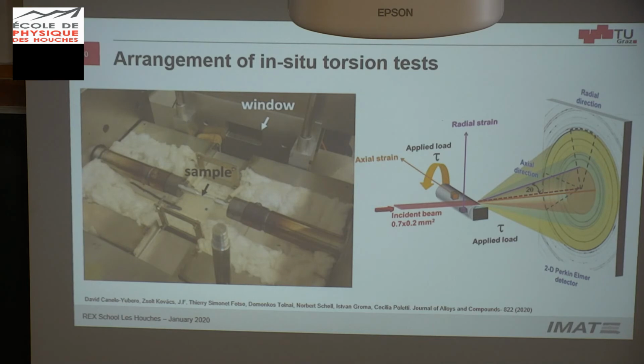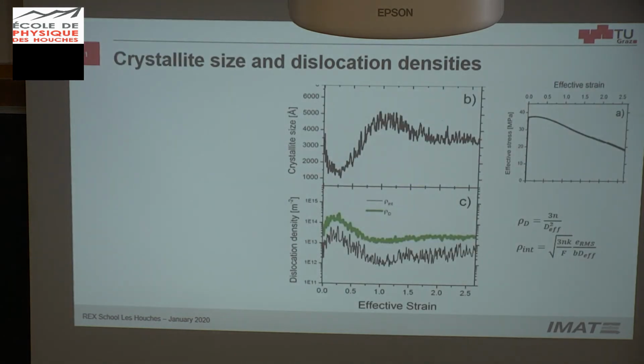You can also see this in the pole figure diagrams. I'm not going to show them here, but I have them in the backup slides if you want. Then we applied the load, and we applied temperature as well. That's why the setup looks like this. Through these windows, we could place the incident beam and obtain the diffraction rings. With the rings we also got the pole figure diagrams, which I'm not going to show here, but we could also get the evolution of the crystallite size and the dislocation density.